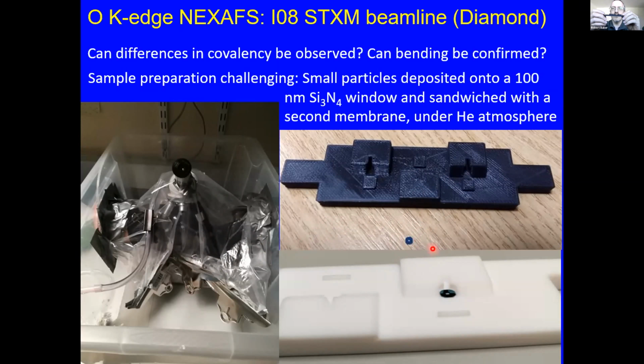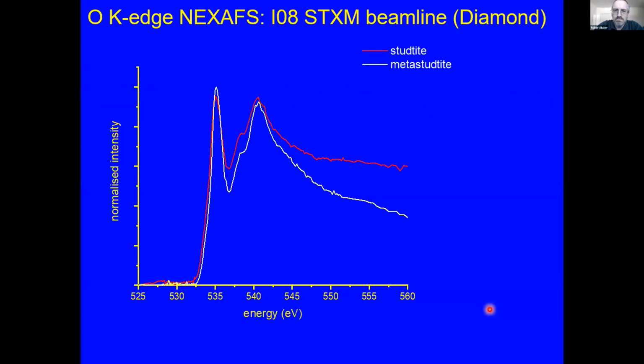I don't know whether my camera is good enough, but this is one of the 3D printed sample holders that we use. And if you can just about see, the sample fits in that really tiny hole here. So I hope this gives you an idea of the scale it fits in there. So it's really, really tricky to be able to manipulate. And it turns out that this was just not good enough to get a good seal. So we eventually milled something out of Teflon, and were able to get the samples prepared and sent to Diamond after a few stops and starts.